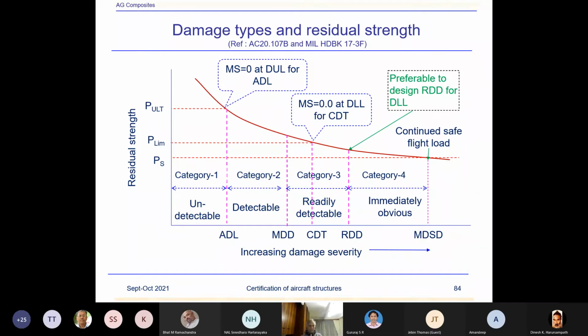So the margin is zero at a certain location of the skin, but at some other location the margin could be 1.5. What happens then when we do the margin survey after the margins are calculated? We try to determine, okay, if the margin is 1 at this particular location, and that margin 1 is defined for a 1/4 inch hole, then can I tolerate a 1-inch hole in that? And so I recalculate the margin equal to 0 for a particular damage. What is my maximum damage which will give me the margin to be 0, because the initial margin for a 1/4 inch hole is 1.